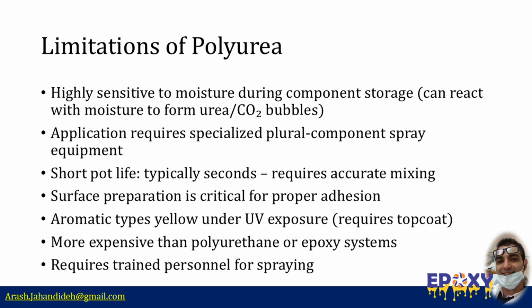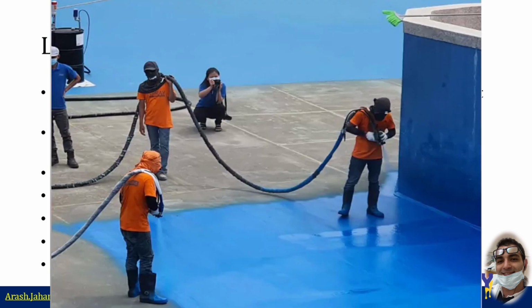Aromatic polyureas, while cost-effective and widely used, suffer from UV instability. They tend to yellow and degrade under sunlight, making them unusable for exposed decorative applications without protective aliphatic top coats. Additionally, the material cost of polyurea systems is generally higher than polyurethane or epoxy coatings. This makes it more suitable for applications where its superior performance justifies the investment.